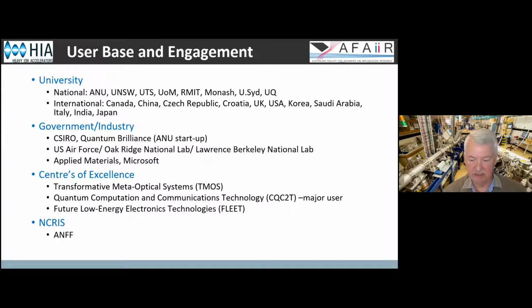It turns out that the coherence between quantum centers is perturbed by the surface, and you need to be well away from the surface to maintain coherence. So that's an example where the full capabilities of our facility are exploited commercially. We do have interactions with centres of excellence, and we've even done some work for FLEET, I think with Julie Carell. We've done some ion beam analysis for her, but we'd certainly welcome any opportunity to expand that engagement.